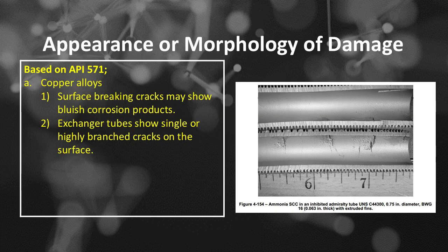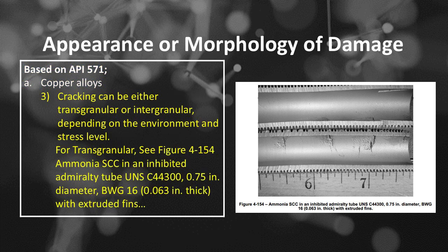Ammonia stress corrosion cracking appearance or morphology of damage based on API 571. Number A, copper alloys, includes: number 1, surface breaking cracks may show bluish corrosion products; number 2, exchanger tubes show single or highly branched cracks on the surface; number 3, cracking can be either transgranular or intergranular, depending on the environment and stress level.